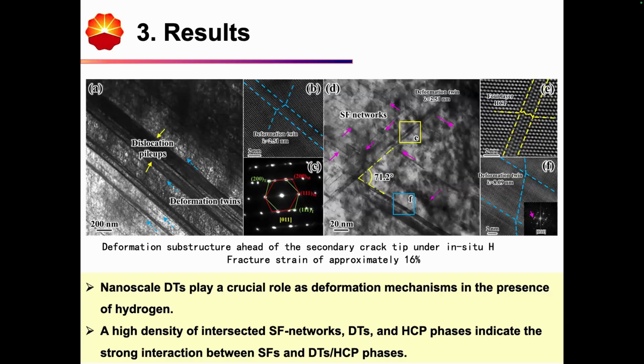And we enlarge the cross-section regions. It shows some cross sections between the lamellar HCP phase and some deformation twins.